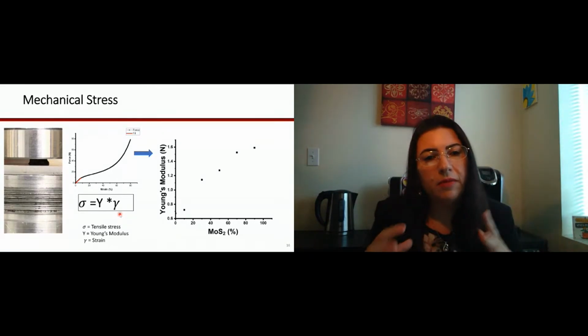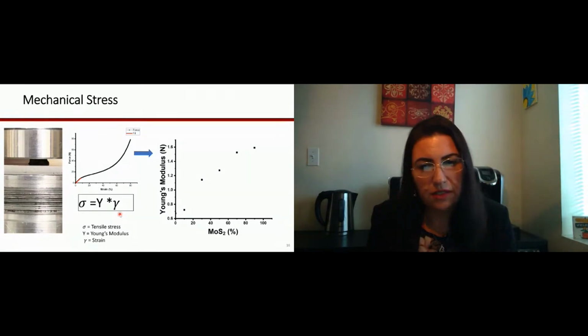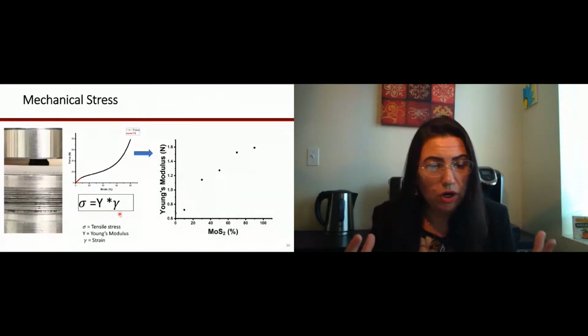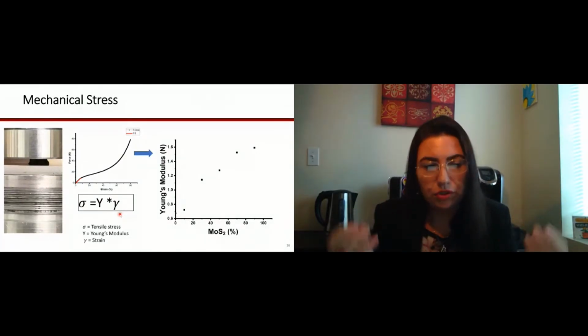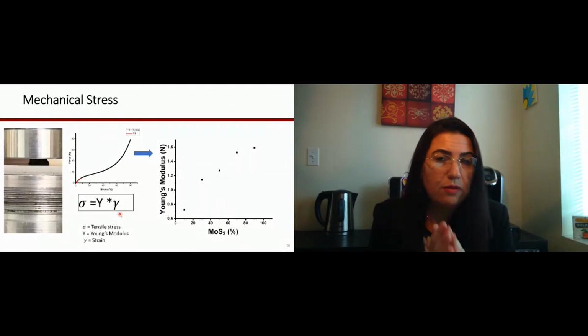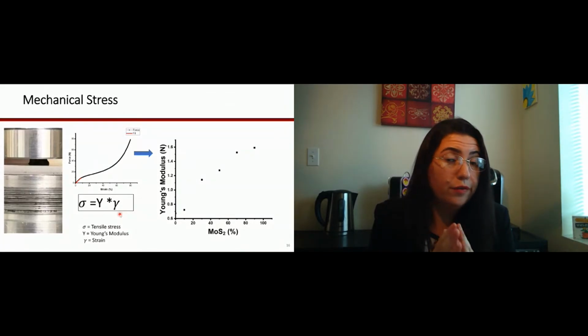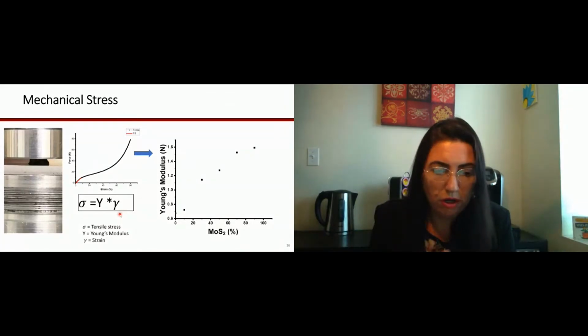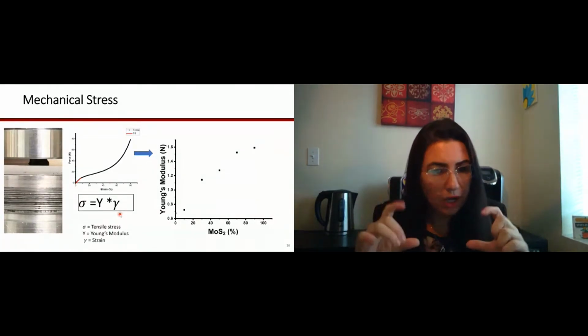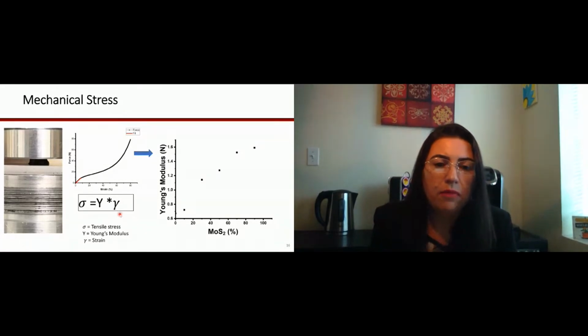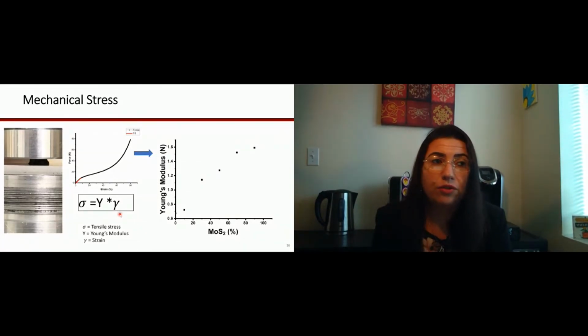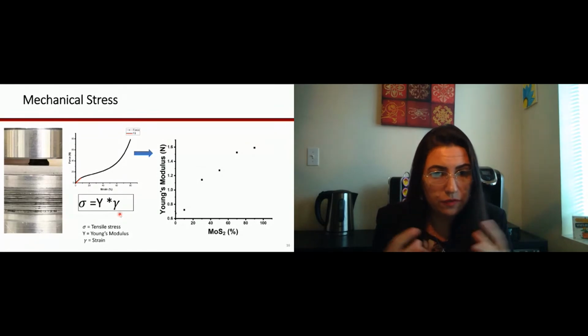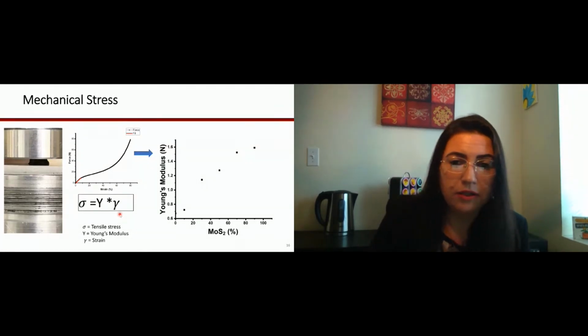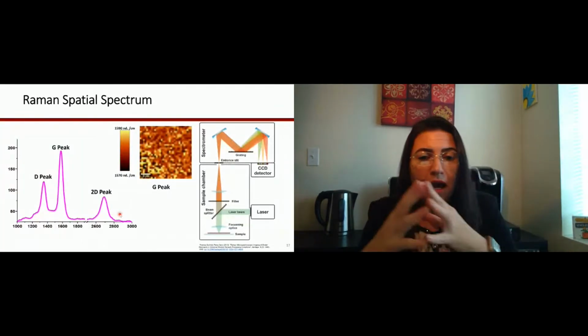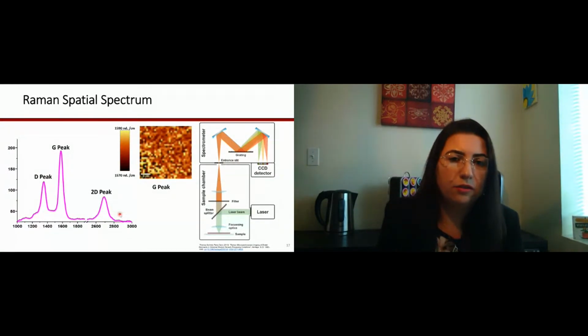So we did all the mechanical stress, and that makes a lot of sense because of MoS2 and all the water. So we did lyophilization, we dry the sample. The sample has a lot of water in it. To remove it, you have all the porosity that becomes easy to crush as we're doing the mechanical stress, and the material does not return at all because of all the porosity. After that, I brought it back and I did the Raman study.